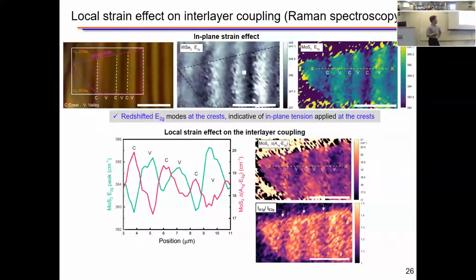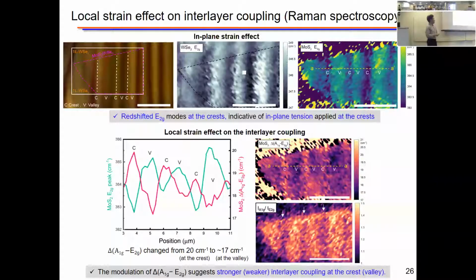Then we look at the local strain effect on interlayer coupling by looking at the mode separation of the A1G mode and E2G mode of MoS2, which can be taken as a mechanical quantitative measure of interlayer coupling strength in artificially stacked bilayer MoS2. The larger mode separation means stronger interlayer coupling. By taking this line profile of multiple wrinkles, we get a mode separation change from 20 at the crest, where we think there's a strong in-plane tension, to a smaller mode separation at the valley, where we expect to see less tension. This suggests stronger interlayer coupling at the crest and weaker at the valley.